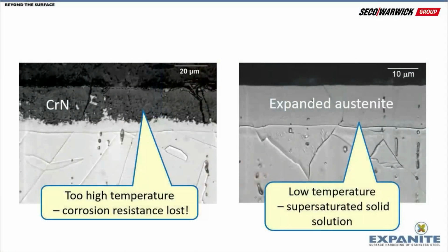But once you have passed this challenge, you are a good way down the line to harden the stainless steel. The second challenge is really the low temperature, because it's quite tempting and quite easy to remove the oxide layer if you just increase the temperature. But you need to be at a low temperature, because if you are increasing the temperature, the chromium will start moving in the system and reacting with the nitrogen and carbon and form what we call nitrides and carbides. And by that, you will lose the corrosion performance. So it's absolutely important that you keep the temperature very low, so it's only the interstitials like nitrogen and carbon that are allowed to diffuse into the material.